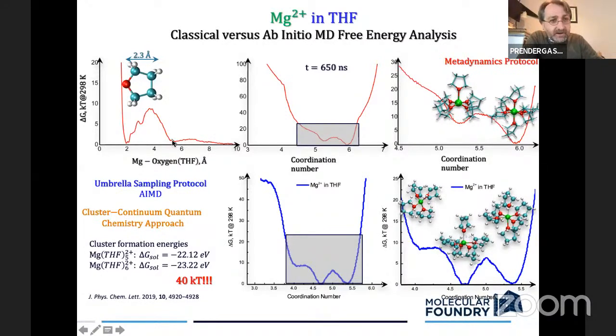There's quite a high barrier to removing this object. This is in units of kT at room temperature, so 10 times kT to pull off one molecule. So unlike water, these organic solvents are quite strongly bound to the species that they connect to. We'll talk a little bit about entropy later, but it has big consequences for that reason.